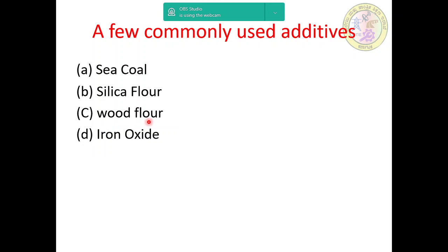It is a pulverized soft wood, that is fibrous material. You have to add wood flour to the molding sand in the range of 1 to 2% by weight of sand. While adding this wood flour to the molding sand, it controls sand expansion created by temper water, and then it absorbs excess water and improves flowability of sand during the molding process. While adding this wood flour, you also improve the collapsibility of molds.